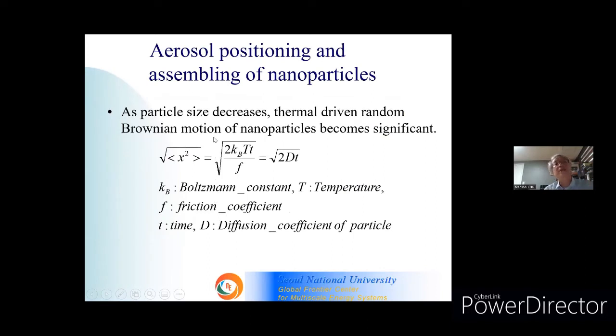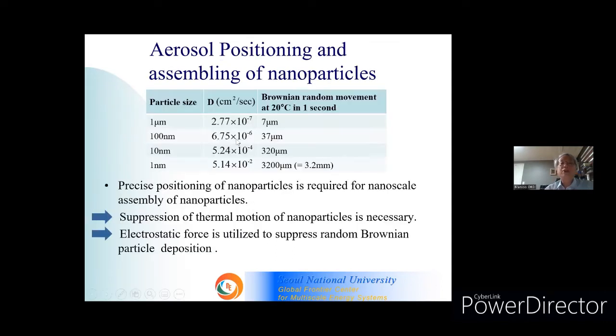When we are dealing with nanoparticles in atmospheric condition, you need to be very careful about Brownian motion, since random Brownian motion is proportional to square root of diffusion coefficient of nanoparticles. And as we all know, if the particle size becomes smaller, this diffusion coefficient will become larger. For example, 1 micron particle moves 7 micrometers due to Brownian motion in normal condition in 1 second. Even 10 nanometer particles could move more than 300 micrometers.